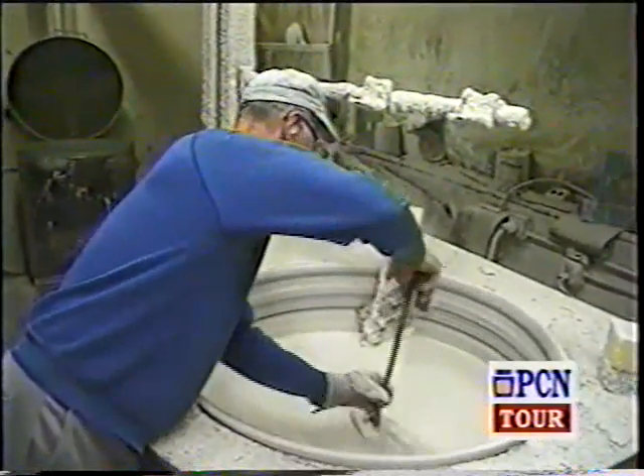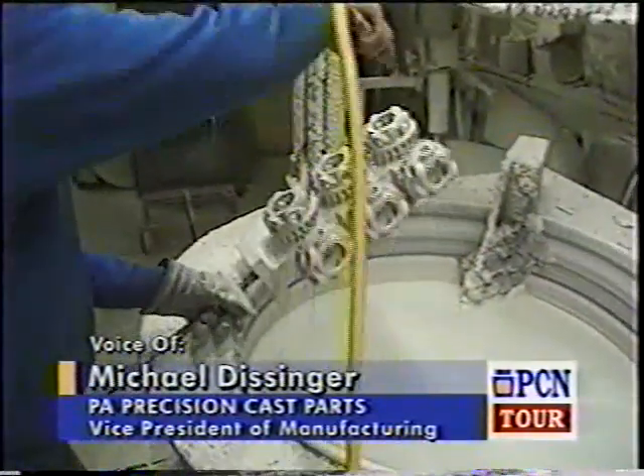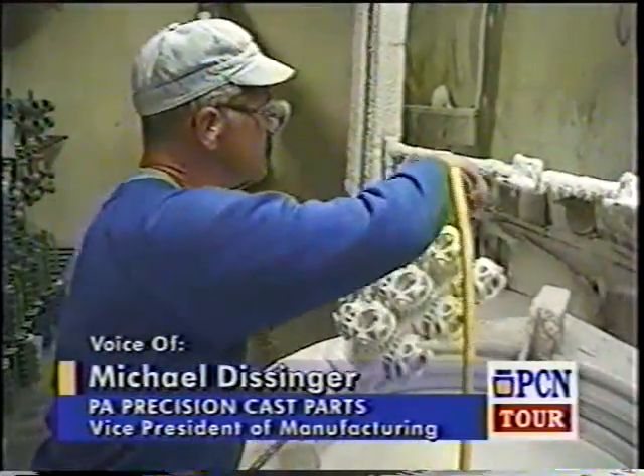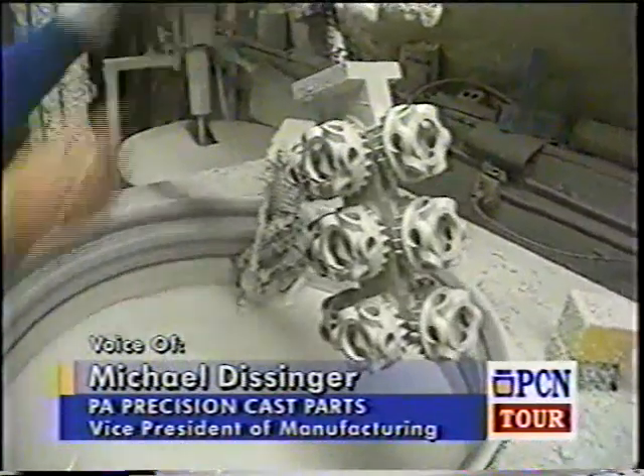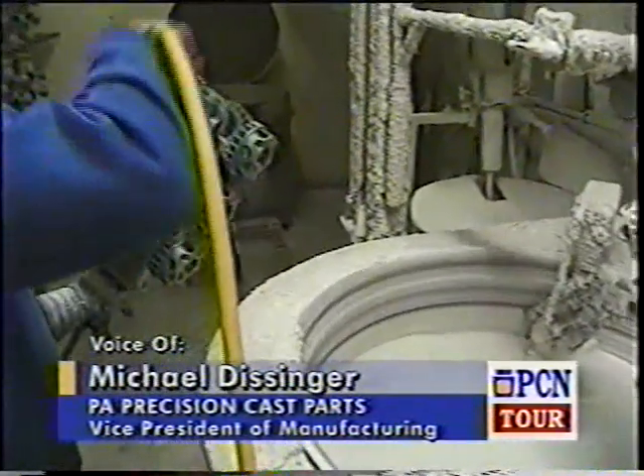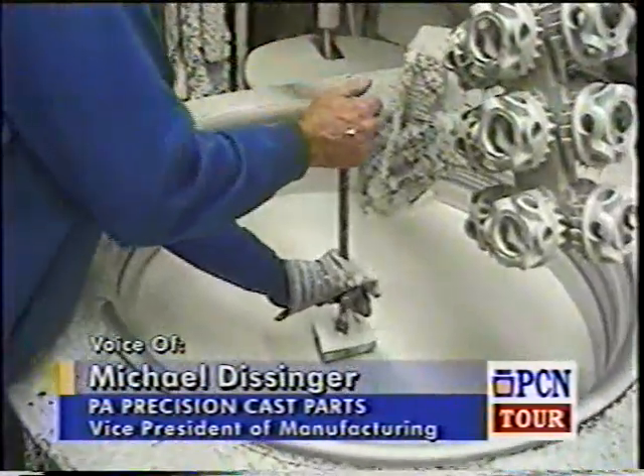All of our dipping is done by hand. The operator will take the assembled cluster of wax and styrofoam and dip it into a primary slurry. The operator will ensure that he has proper coverage inside all the cracks and crevices to ensure proper detail. He removes it from the slurry, checks for any air bubbles as well as for proper coverage, allows it to drain, and after about 30 or 40 seconds, he'll then take the mold and immerse it into a fluidized bed of zircon sand.